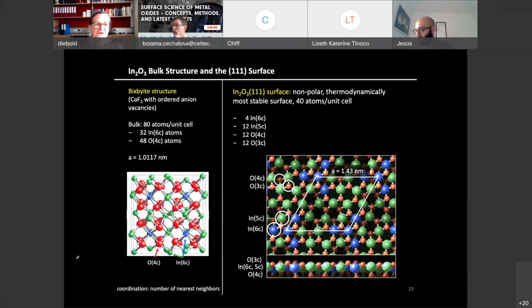Let's go to this other material that we'll talk about, indium oxide. I'll tell you in a second why it's interesting. In the bulk, it looks really complicated. This is the unit cell. It's a cubic unit cell with a 1 nanometer lattice constant. So it's a cube 1 nanometer in size. That's really big. Inside of this cube are 80 atoms: 32 indium atoms that are 6-fold coordinated, meaning octahedrally, and then 48 oxygen atoms that have 4 nearest neighbors.